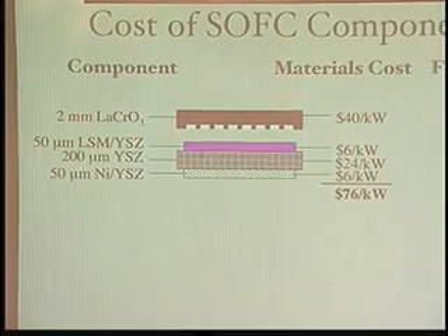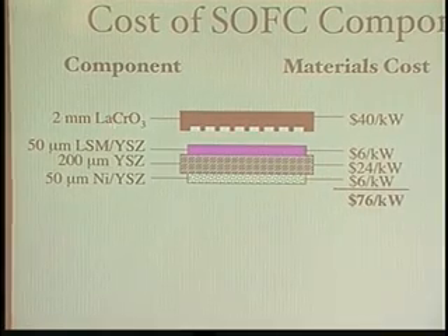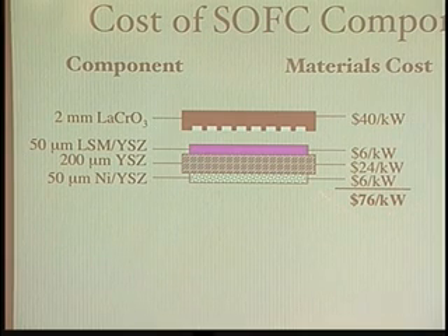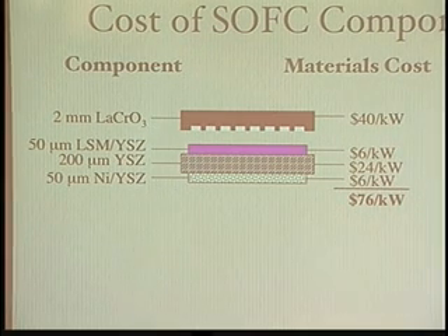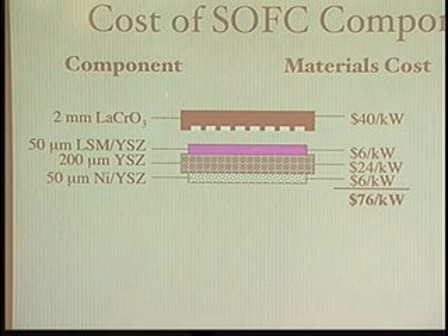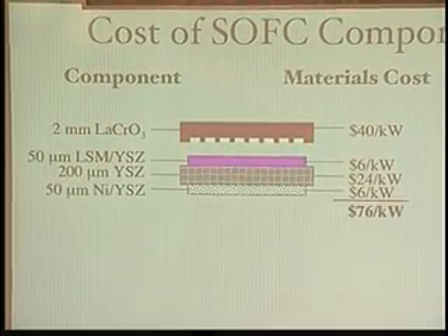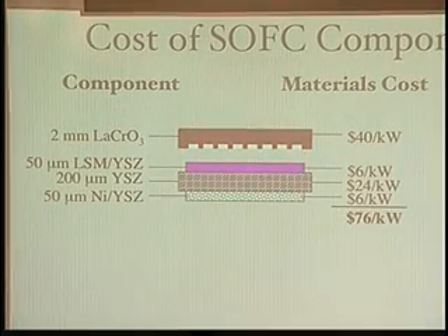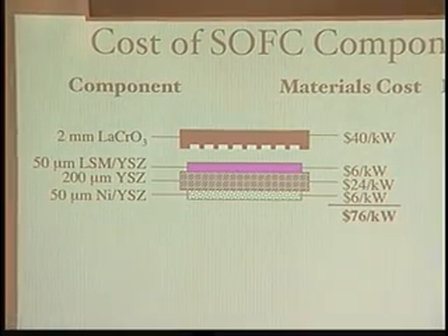It was typically made from something called lanthanum chromite, which is a conductive ceramic. If you add the costs up, this is the dollars per kilowatt for just raw materials. And that's not too bad, because remember, the target cost is $400 a kilowatt. The problem is, these are actually flow channels. The hydrogen and the air have to come into this device and run across the electrodes. And to make a machined ceramic is very, very expensive. It's not like machining metal. It's actually quite expensive. And so this has largely been abandoned because of that cost.